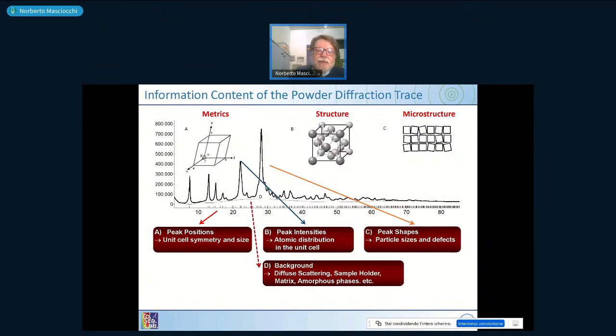So you've seen already that the powder diffraction gives you a sequence of peaks overlaid on a background. Why are the peaks there, and why do you have this intensity? The peak positions give you unit cell symmetry and size, independently of the intensity which you measure at any peak position. The peak positions are labeled here with some peaks which are easily detected by carefully searching for the presence of relative maxima in the powder diffraction pattern.